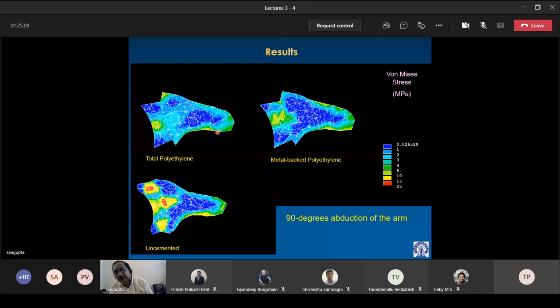Okay. If you induce a metal backing, a very thin metal backing of 1 millimeter or 1.5 millimeter, immediately you see the difference. More stresses within the implant and less stresses in the adjoining bone. If you increase the metal backing, as in the case of uncemented prosthesis, no cement here, remember, you see how high are the stresses within the implant and less within the bone.